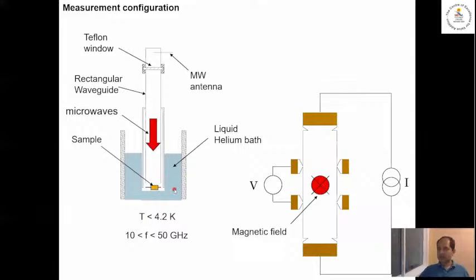And so we measure resistance versus magnetic field. We do this at low temperatures below 4 Kelvin, which is 4 degrees above absolute zero. And we change the microwave frequency between, say, 10 and 50 gigahertz.